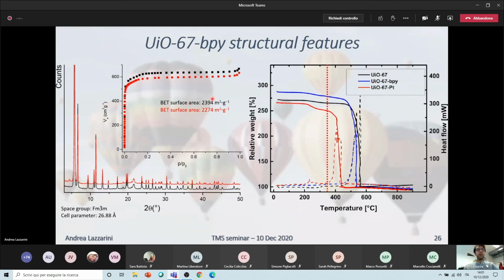The only weak point of these materials is that since they are hybrid in nature, so they have both metal and organic parts, they can be weak from the temperature point of view. As you can see by the thermogravimetric analysis, we were heating the UiO-67 systems in air, and after a certain point, they started to degrade and lose all the organic parts, becoming basically zirconia. So we decided to keep our temperature limit to 350 degrees in order to save our material in the reaction.